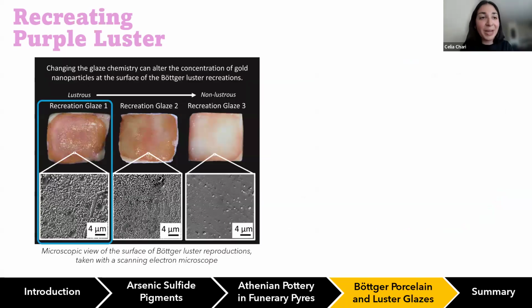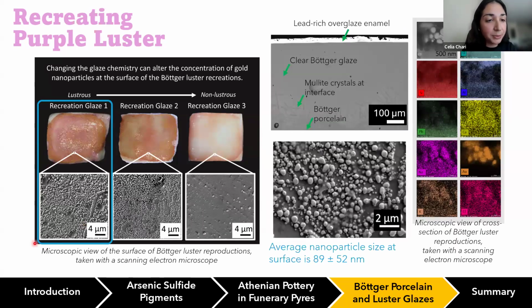So this is the purple luster that I recreated. These are different versions of it. The most successful one is shown here in blue. And this is just a cross-section view showing that very close to the surface, we see the presence of these gold nanoparticles. Now, within the glazes that I produced, the sizes of the gold nanoparticles also varied.